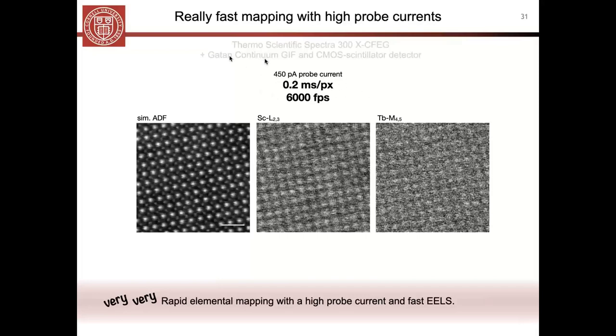This is the maximum frame rate of the Continuum GIF and CMOS with scintillator detector that we have on this instrument. And so with that much bigger increase in the maximum frame rate, up to 6,000 frames per second, we can do this very, very rapid elemental mapping. The total time for this map is about 7 seconds. So now we're starting to approach the time scale of the HAADF image, with a frame time of 1 second.